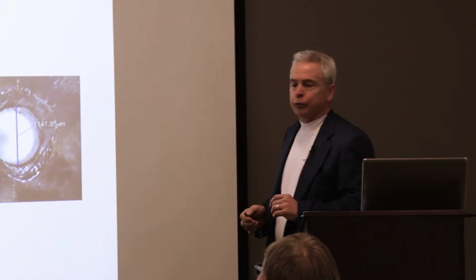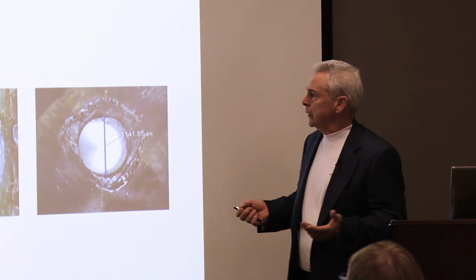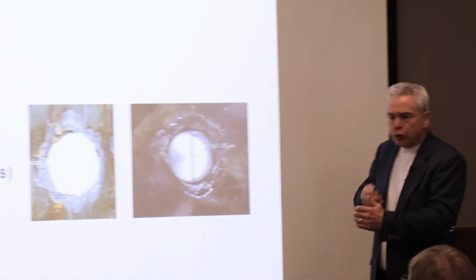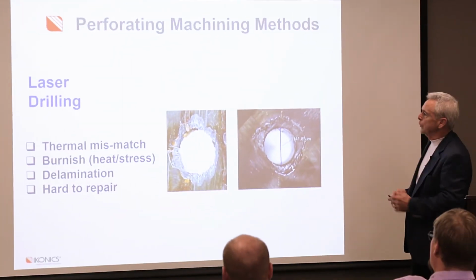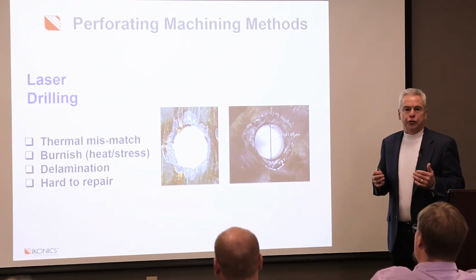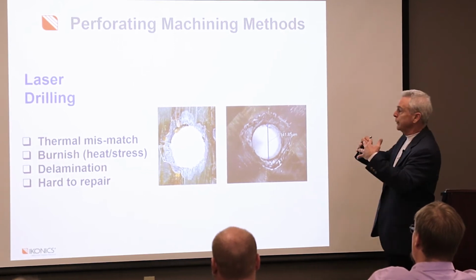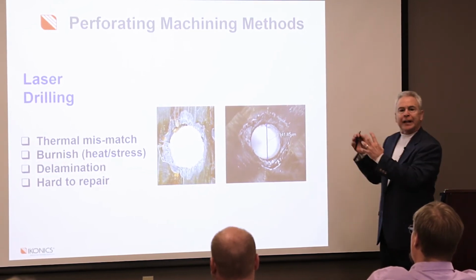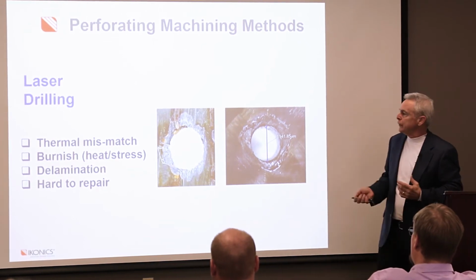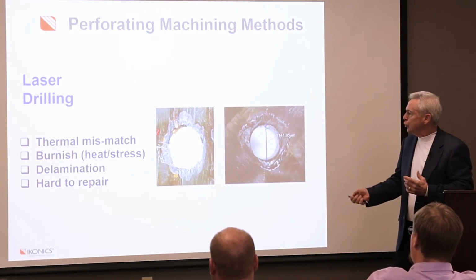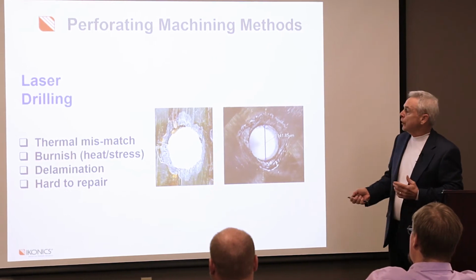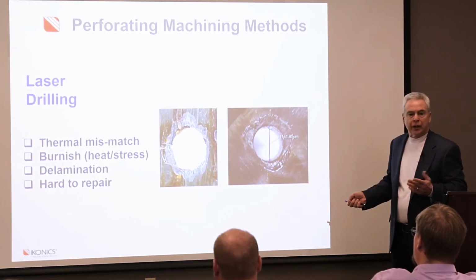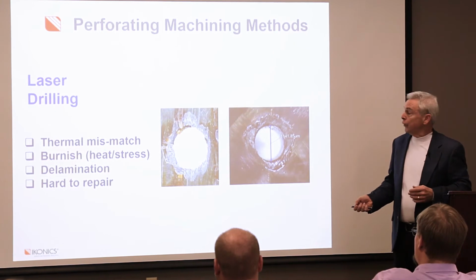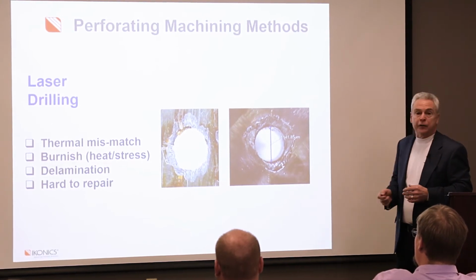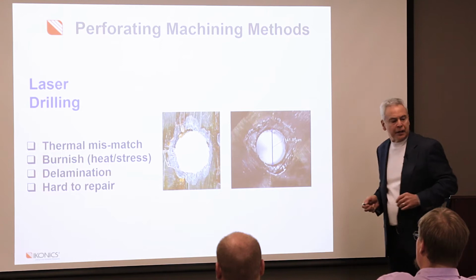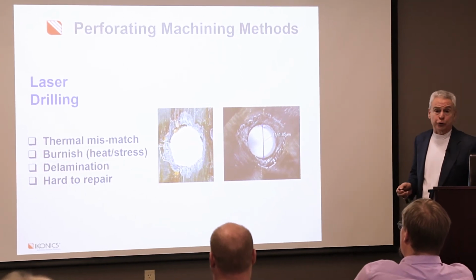And the last one, which is really the least popular and not often done, is laser drilling. And they're trying to get this more into the industry, but there's a major issue here. We talked about that thermal mismatch before between fibers and epoxy. So you can't get the right energy balance into the laser in order to get a good uniform image without causing burnishing, heat, stress, delamination, and again, very hard to repair any of these if they occur. So that's why this one is not as popular as the other two methods are.